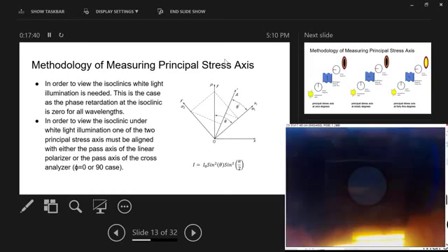So we basically take advantage of this property right here, this intensity profile, to determine the direction, because our object, when the predominant direction of surface is in line with our polarizer or analyzer, will return no intensity, right? Because of this theta right here.